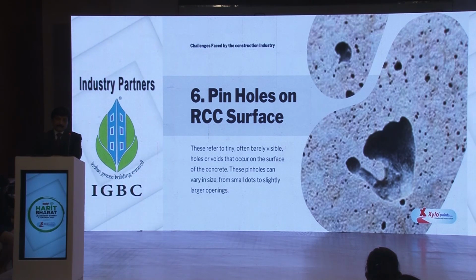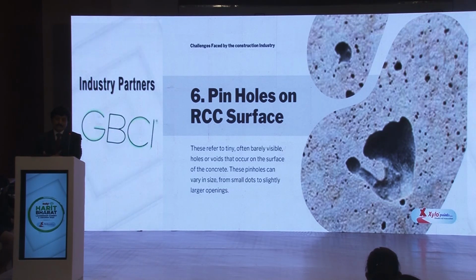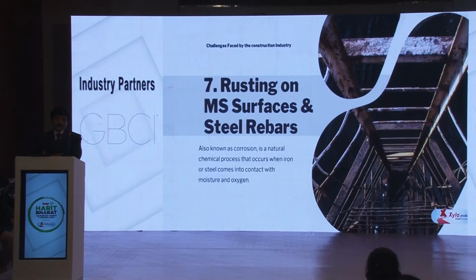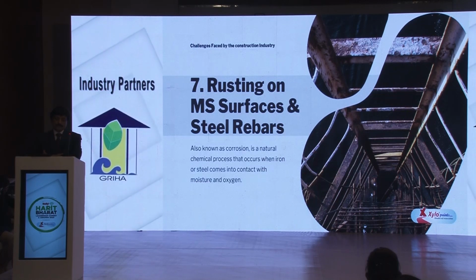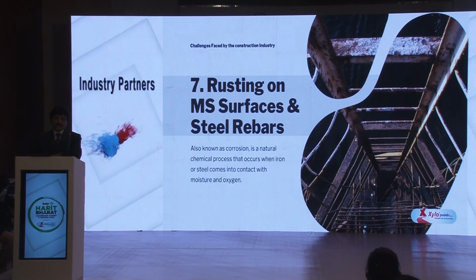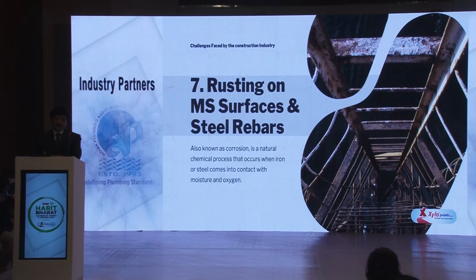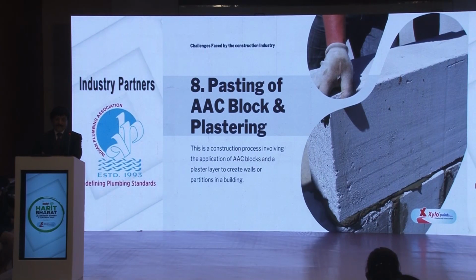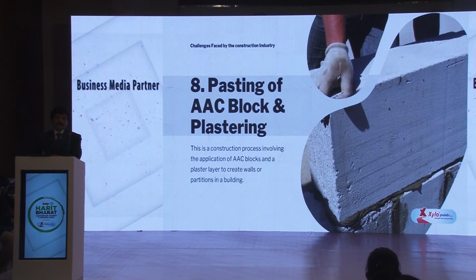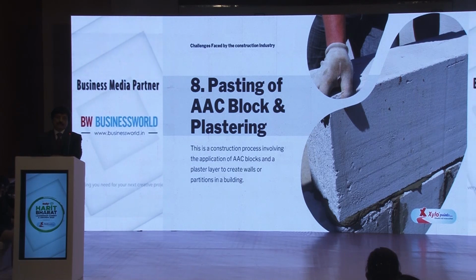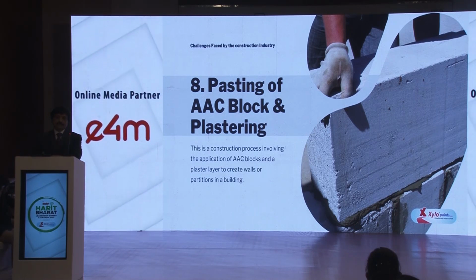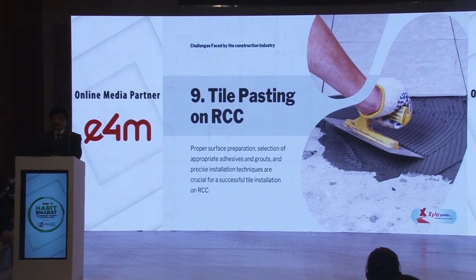Pinholes on RCC surface. These refer to tiny, often barely visible, holes or voids that occur on the surface of the concrete. These pinholes can vary in size, from small dots to slightly larger openings. Rusting on MS surfaces, the steel rebars, also known as corrosion, is a natural chemical process that occurs when iron or steel comes into contact with moisture and oxygen, pasting of AAC block, and plastering. This is a construction process involving the application of AAC blocks and a plaster layer to create walls or partitions